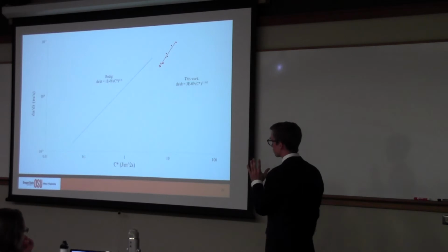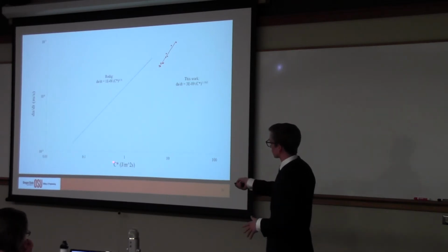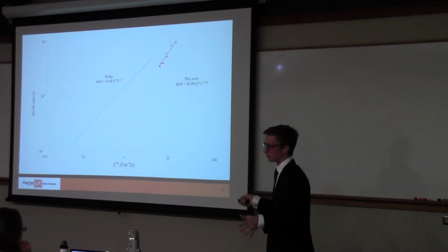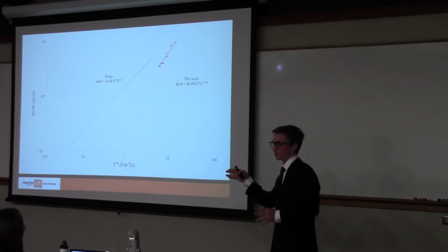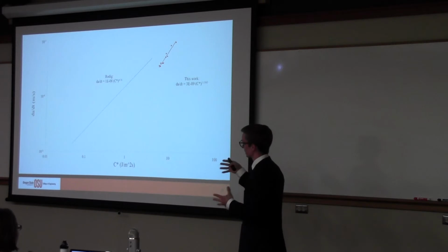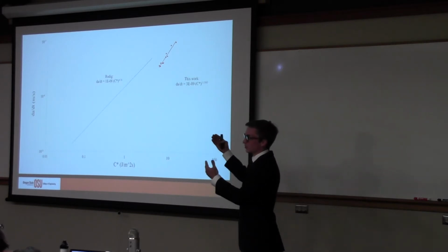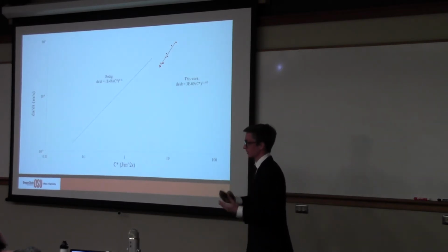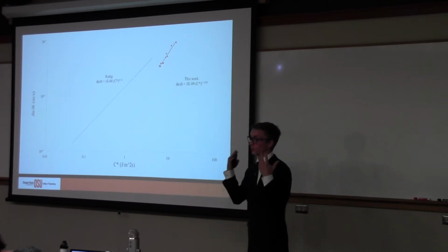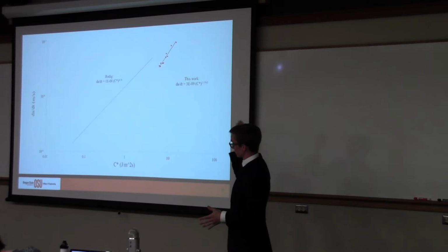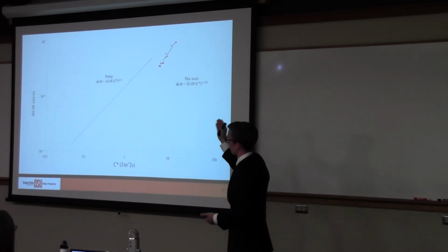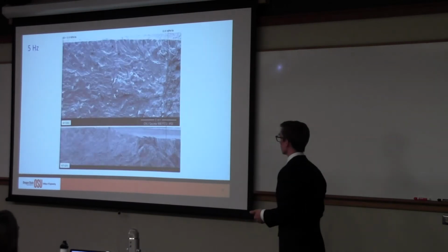I'm not going to say too much about this graph other than, oh, what's that? It's C star. It's a time-dependent parameter, and it's difficult to gather. And all that extensometer feeding through the induction coil, that's what allows us to get this, which allows us to get the transition time of the material, which tells us something important about the use of K in general. Okay, and all I want to point out here is that from some studies that were done in the 90s, our data coheres decently with their power law that they got out of it.